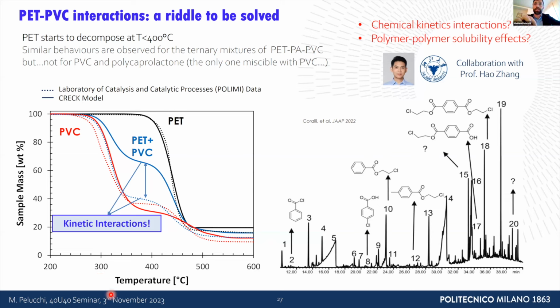There are studies in the literature where they measure the products from these mixtures, and you actually see clearly that the products are made of monomers of polyethylene terephthalate, something that resembles terephthalic acids with some chlorinated part. These clearly indicate some sort of kinetic interaction between one and the other.